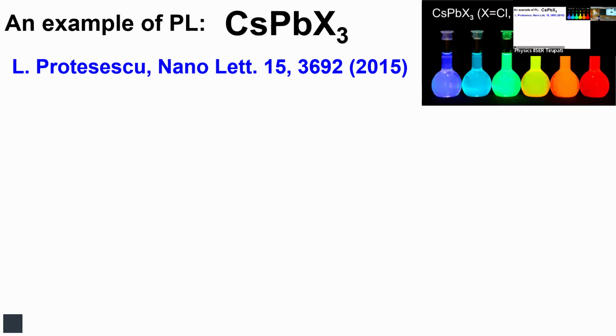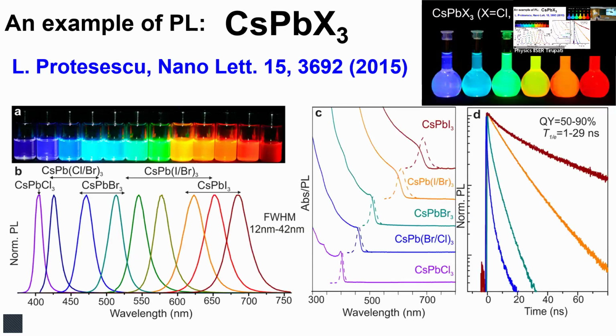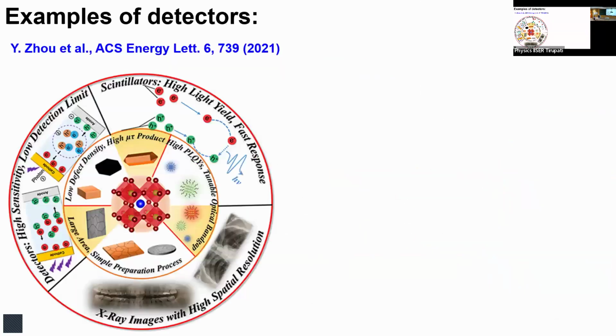It's brilliant. For every 100 photons that you give in, how many photons come out is the measure of quantum efficiency of any light emitting device. The light emitting devices that are normally used are at best in the 30–40% efficiency. But these materials approach a quantum efficiency of 90%. And that's why here you can see the quantum efficiency is from 50 to 90%. And you can cover the entire visible spectrum, which means that you can combine them to have lighting and many other applications. And people are going ahead in a very serious way in utilizing them.